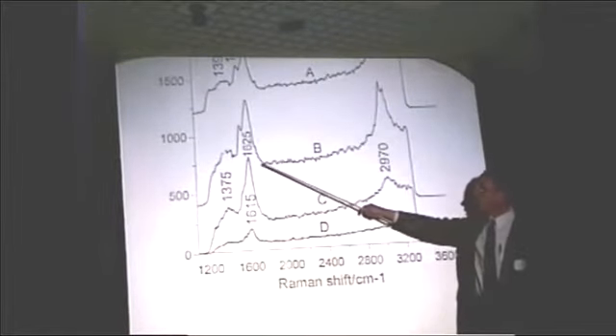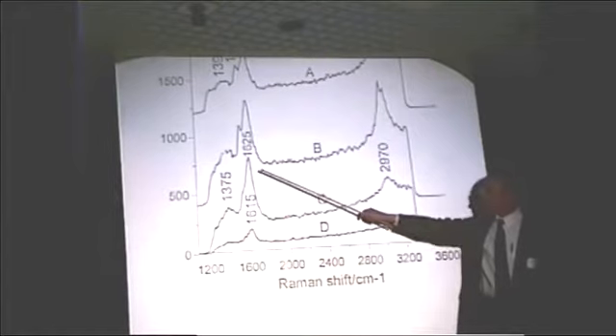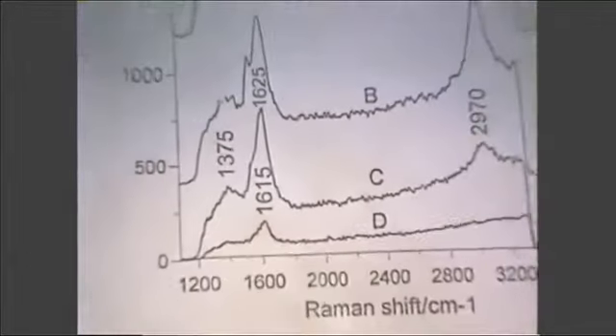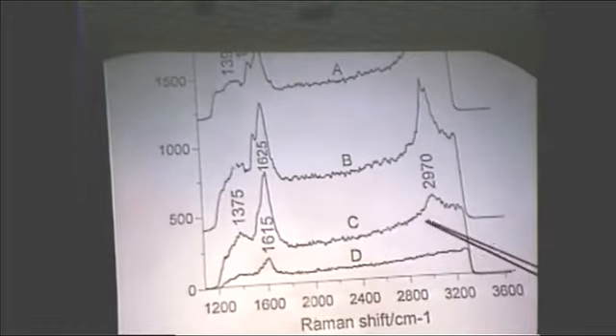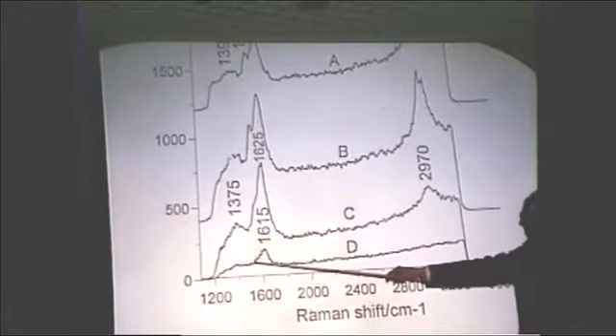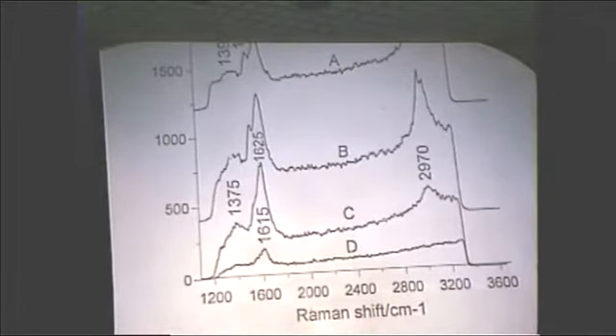Now if you go over 3 hours at 500 C, then you get the spectrum shown here with C. Clearly some changes have taken place in the nature of the coke. We've lost hydrogen, and this band here, which was at 1635, has shifted to 1625, so it's shifted down. This spectral position is about what you'd expect for aromatics on the surface, for the ring breathing modes or the CC stretches in aromatics adsorbed on the catalyst. If we then just remove the propylene from the feed altogether and just purge in helium at 500 degrees, then virtually everything comes off the sample except for some small residual band here at 1615 wavenumbers, which is shifted down somewhat more from 1625.